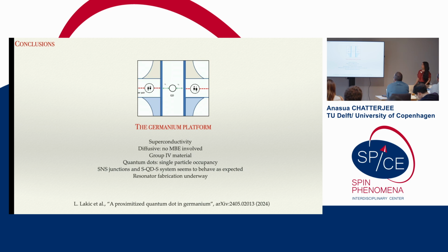So to conclude, we've been exploring the germanium platform because we want to make these circuits of superconductor and semiconductor systems. We want to get to a coherent, quantum coherent, transparent interface, and we want to be able to make nice dots and nice resonators. And so what we have achieved is that we can see superconductivity. We don't have to do MBE growth or epitaxial matching. We have a group 4 material. We can get down to the single hole limit. We can make kind of an SNS junction and an SQDS system. And we are currently fabricating resonators on this system, and the paper is out on the archive.